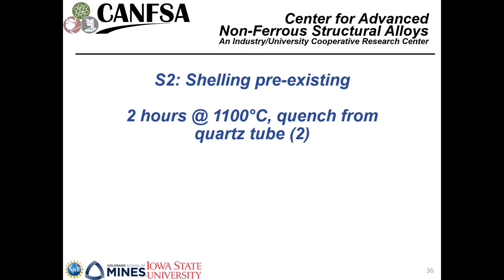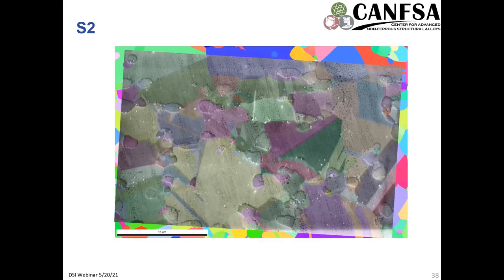And we did some high temperature heat treatments, 2 hours at 1100 Celsius, to try to allow the material to approach an equilibrium state and for consumption of that shell by either the neighboring grains, gamma grains, or whichever mechanism would occur. However, we still observed a fair amount of stability of that shelling in multiple regions within the material.